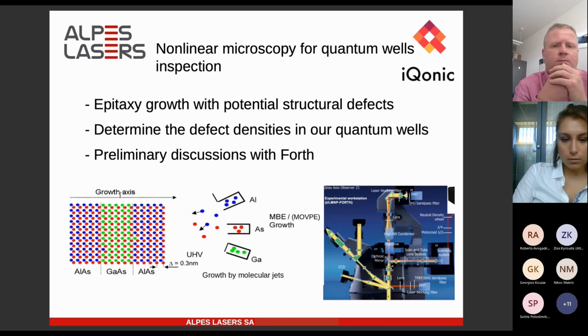And this is very challenging because we have tried a lot of different techniques for that. This is really important for us, because if this growth is not good, we should stop the process at this step, because the next steps are very expensive. But so far, we did not manage to find a good method to really find the defect distribution inside our wafer. So we have had some preliminary discussion with Forth about this issue, and I think we should push that forward.